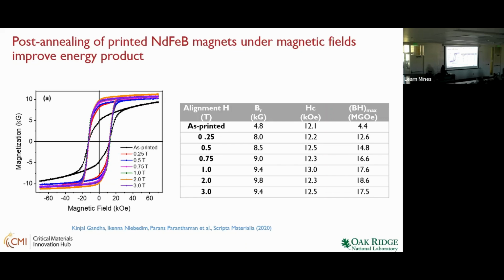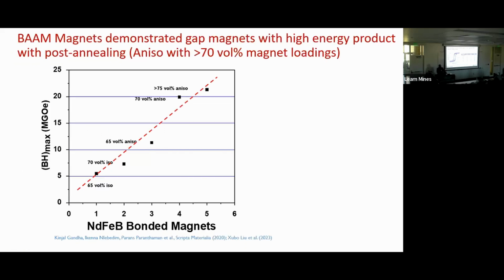When you apply a field, it improves, and you can see the saturation, the Br remanence, coercivity and the energy product go from 4.4 MGOe all the way to 17 to 18. All of this is post-magnetic field annealing. That's the challenge when you want to make a large printed magnet. You can print magnets, but the post-magnetization is hard. We have done small sections like 2 by 4 by 6 into a magnetic field, and you can anneal and do that.